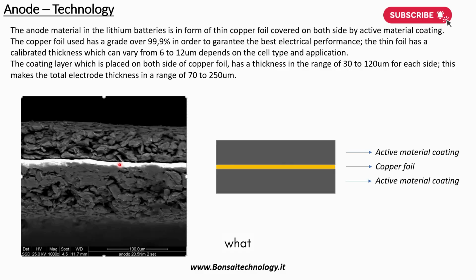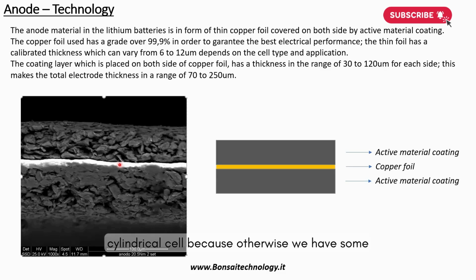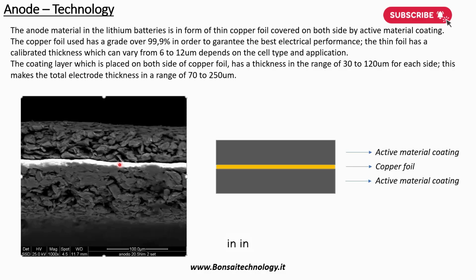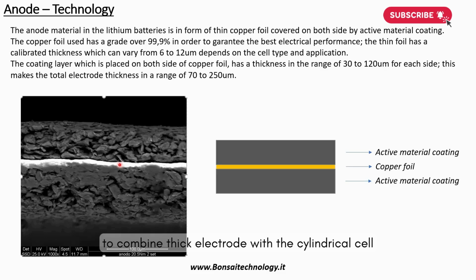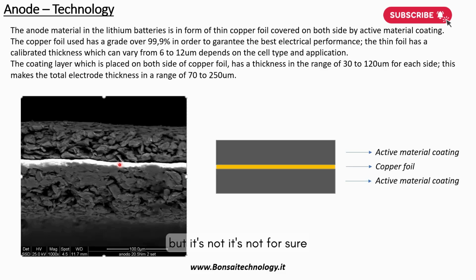The same of what we said before about the cathode is still valid even for the anode. I mean, very thick anode material cannot be used for cylindrical cell because otherwise we have some problems in the beginning of the winding process. But for sure it can be used in prismatic and pouch. There are some exceptions, as always. For example, Tesla is using very thick electrode material in their cylindrical cell. There are some strategies to minimize the risk and to combine thick electrode with the cylindrical cell, but it is for sure not easy to achieve.